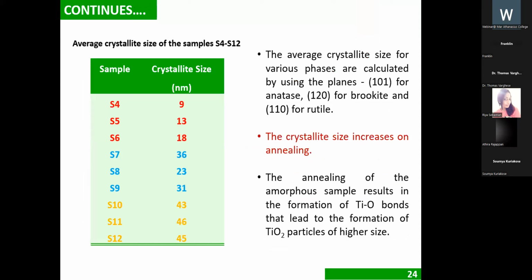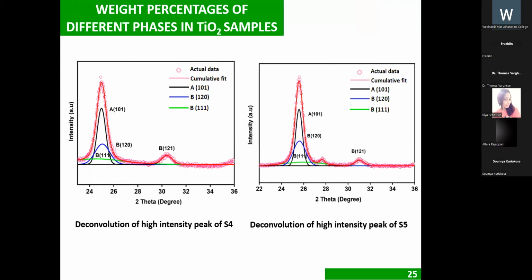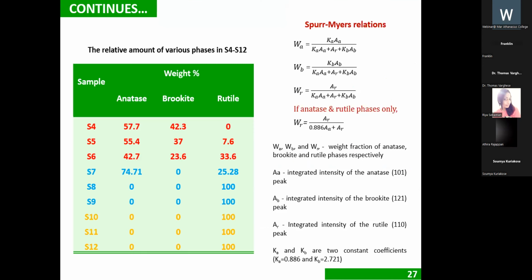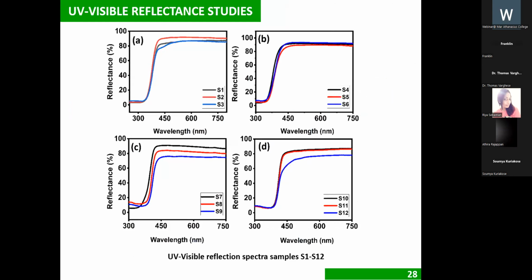Then the average crystallite size is calculated from the Scherrer equation, and it is listed in the table. And as the annealing temperature increases, an enhancement can be observed in crystallite size. Then, in order to find the percentages of the anatase, brookite, and rutile phases of TiO2 in each sample, I deconvoluted the XRDs, and the different weight percentages are listed in the table. It is visible from the table that as the amount of oxalic acid increases, in all cases, an enhancement can be observed in the amount of rutile phase of TiO2. But in the case of the final samples, that means from S8 onwards, irrespective of the amount of oxalic acid, only rutile phase is there, because this high temperature gives only the stable rutile phase of TiO2.